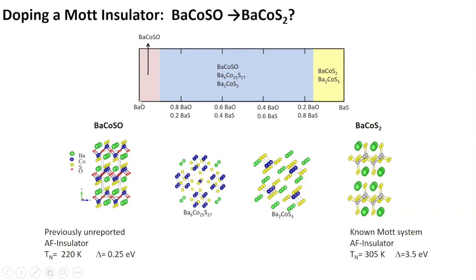And when you are approaching the absence of sulfur down at this end, the barium cobalt sulfur oxygen phase, which is shown here, is what is stabilized. At the time, this material had not yet been reported. It is a new antiferromagnetic insulator. It has staggered planes of cobalt and lower Néel temperature and a very small gap. And it's for this reason that we would be potentially interested in it for applications.